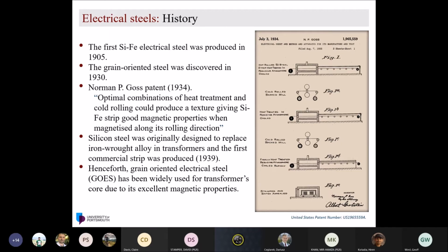grain-oriented steel was discovered. Later, in 1934, Norman Goss patented it, and I'm showing the United States patent number here. It's very nice when you look at that patent, because it's actually not much different from the way we write about thermomechanical processing today. What Norman Goss patented in 1934 was that a good combination of chemical composition along with thermomechanical processing and suitable heat treatment gives a texture for silicon steel with good magnetic properties when magnetized along its rolling direction. After 5 or 6 years, in 1939 and 1940, the first commercial Goss grain-oriented electrical steel was produced, and since then it has been widely used in transformers.